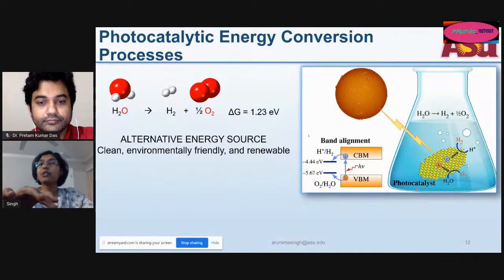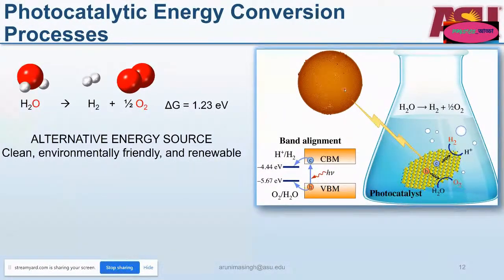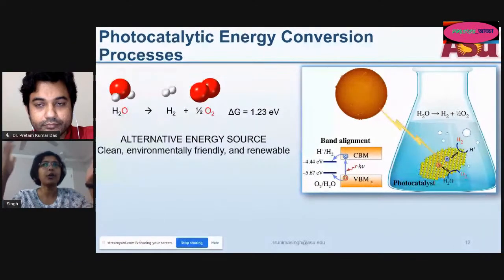So even though this is not a spontaneous reaction, if you use solar light of sufficient energy, and use a photocatalyst which has suitable band gaps and band edges, you can generate electron-hole pairs where the electrons and the holes will catalyze redox reactions for this conversion. What you require is that the band gap of your material should be larger than 1.23 eV, and its band edges should straddle the potentials for the redox reactions of water splitting. So that's an intrinsic property of a photocatalytic material. If I was able to find materials which satisfy this condition along with others, then I might be able to use sunlight to convert water to hydrogen gas and oxygen gas.